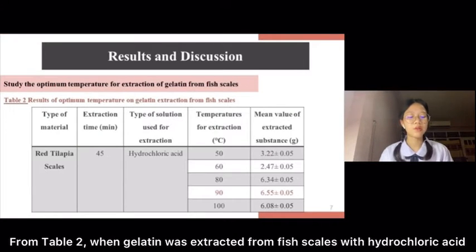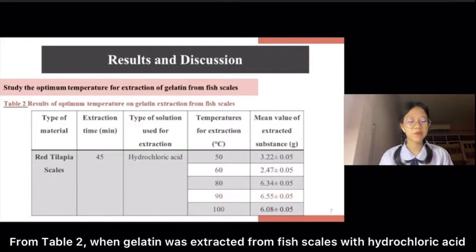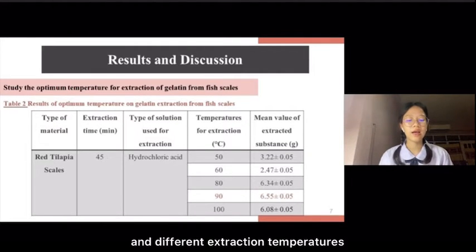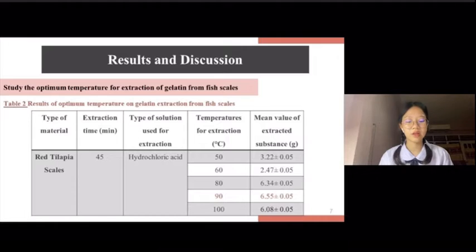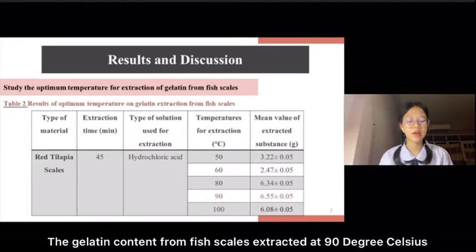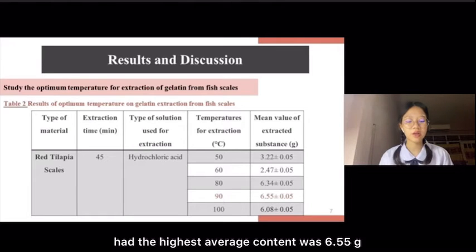From Table 2, when gelatin was extracted from fish scale with hydrochloric acid at different extraction temperatures, the gelatin extracted at 90 degrees Celsius had the highest average content, 6.55 grams.